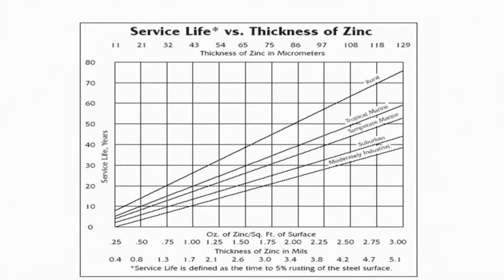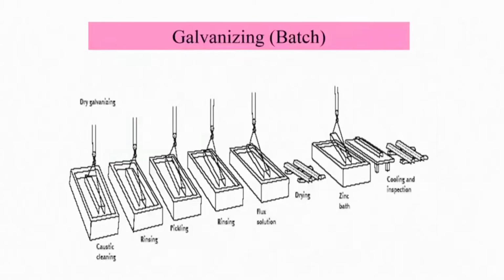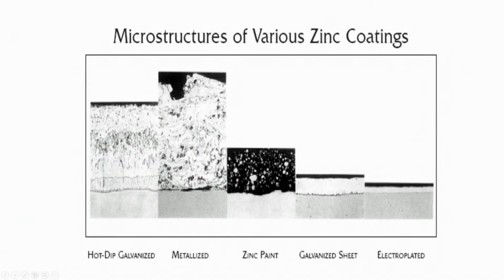So, the service life is basically a relative term; it depends on the environment where the component is used. But whatever the environment may be, as you go on increasing the thickness of the zinc coating, you increase the service life to a large extent. As I mentioned, among all these parallel techniques, hot dipping offers the maximum thickness with a strong interface, and the metallizing or thermal spraying route also offers a similar level of thickness, but the interface is not as strong as in hot dipping.